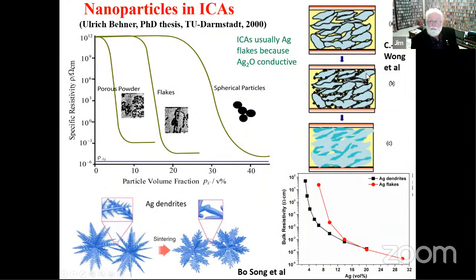But then C.P. Wong at Georgia Tech used the nanoflakes, nanoparticles in between silver flakes here. They still had a higher resistance because of the contact resistance to the silver nanoparticles, and the mean free path in the nanoparticle was very short, and so on. But then heating them up, if you remove that coating that they came with, they sintered the flakes together, and you got a dramatic reduction in the resistance from going from here to here.